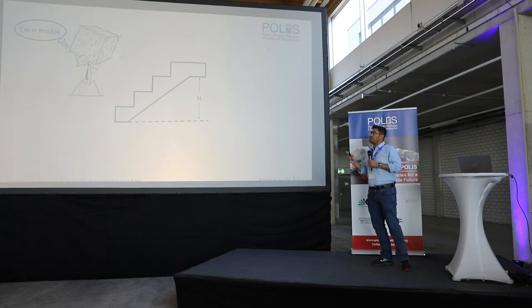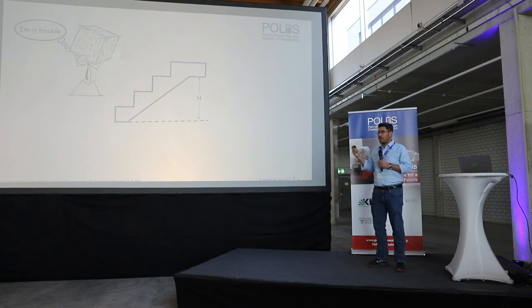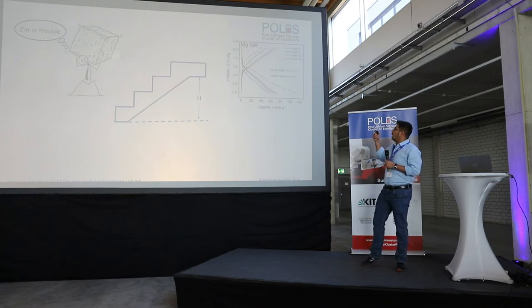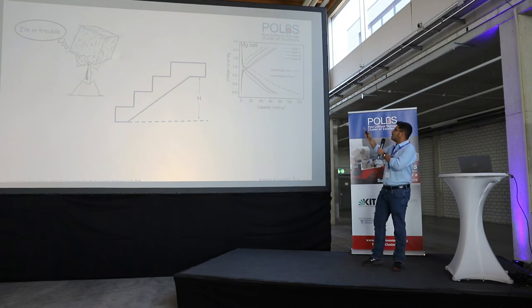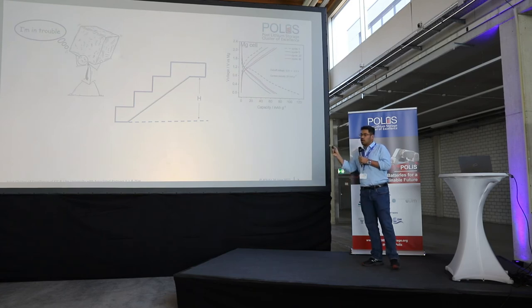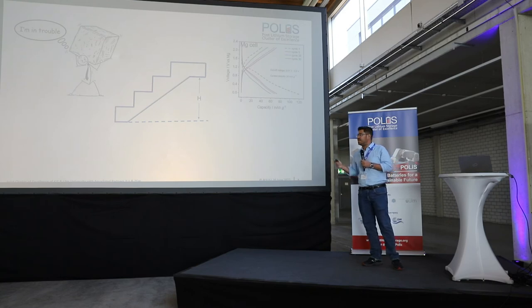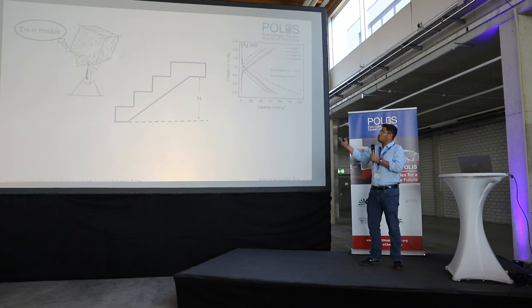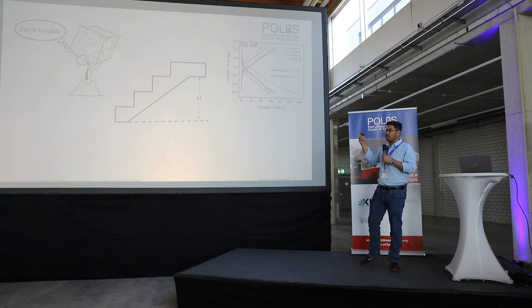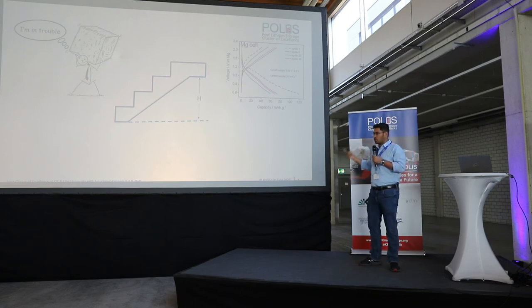He is slow, and he is doing something which is extremely energy intensive. And this is very synonymous with what happens with magnesium ion insertion when it comes to cathode materials. And that gives us a capacity which is slightly on the lower side, and on top of that we have these sloping voltage profiles. Now the reason is that magnesium, being a plus 2 charge divalent cation, interacts very strongly, similar to this guy who is carrying a heavy load and needs to go up a staircase, which means he has to work against the field of gravity. So again, the concept of potential energy is coming into this. And in batteries also, we learn about potentials that need to be overcome.